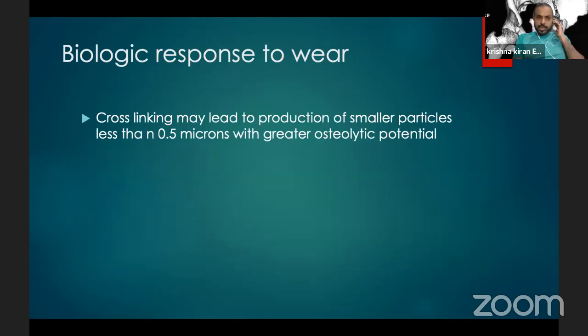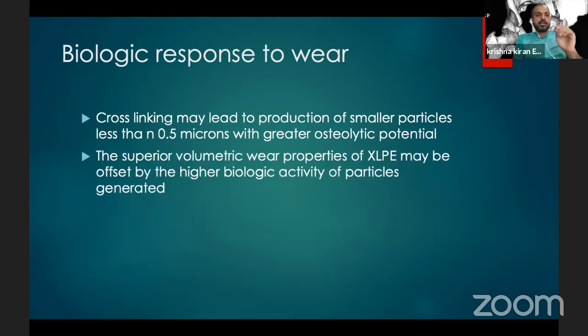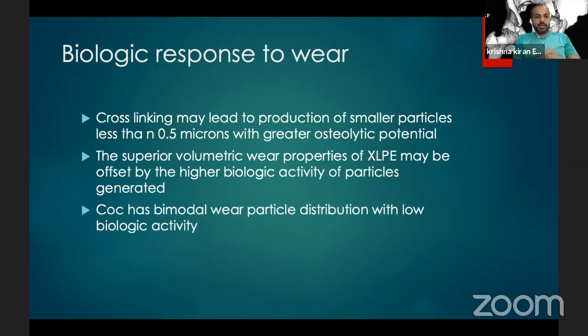On the biologic response to wear of different bearings, cross-linking will reduce the production of particles, but there may be some smaller particles, less than 0.5 microns, with greater osteolytic potential. This has not been borne out in 15 years, but we must see in the future. In general, the superior volumetric wear properties of XLPE offset the higher biological activity of the particles.